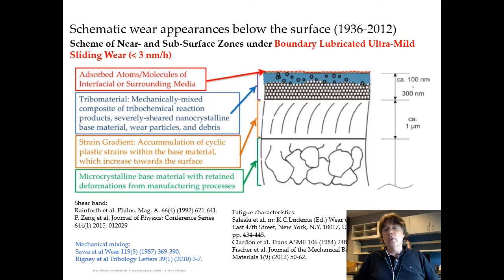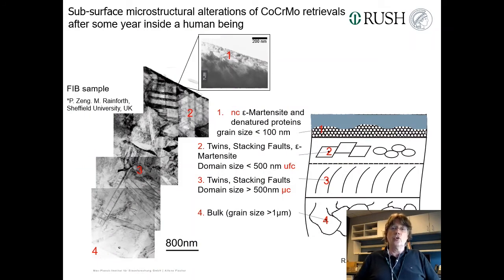And all of a sudden, always over a very sharp line, you get some nanocrystalline stuff, more or less generated by severe plastic deformation, quite similar to shear bands. And that might incorporate some stuff from the environment as well as from the interfacial medium, for instance, in the lubricated contact. For instance, if you do this from a hip joint, cobalt-chrome molybdenum alloys, Mark Rainforth and Dr. Zheng helped us with this years ago. So you have the base material with some stacking faults and twins, and then towards the surface, the lattice defects increase until you get this peculiar structure. So here there's nothing, while everything just goes on what we call discrete sliding planes. And then you have this very sharp line above which everything is nanocrystalline. And more or less this structure follows very nicely this sketch.